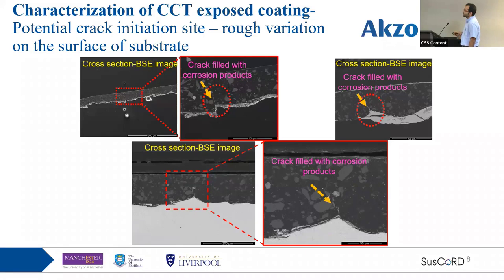I think probably due to the geometry of the substrate, this generated a stress field and stress concentrations within the polymeric binder that eventually resulted in crack formation due to the exposure. And then the corrosion process has started from the defect, penetrating underneath the coating, and reaches here and fills the crack. These bottom figures are for a coating which is far away from the scratch.